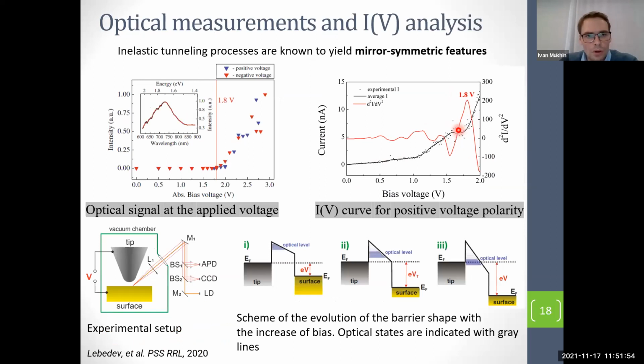To prove that, we combined our experimental setup with an optical scheme and collected light simultaneously. And we change the voltage applied to our contact, and here you can clearly see that light starts to be emitted at a voltage of about 1.8 volts, which corresponds well to the features on the IV curve. So to explain this IV curve, a simple model can be considered. If voltage is low, we have a trapezoidal shape of the barrier, and we have high resistivity of our contact. At the transition point, we change slope from one to another, and when we apply enough voltage, which corresponds to the energy level of optical states, we open the inelastic tunneling process, and we have features on the IV curve.